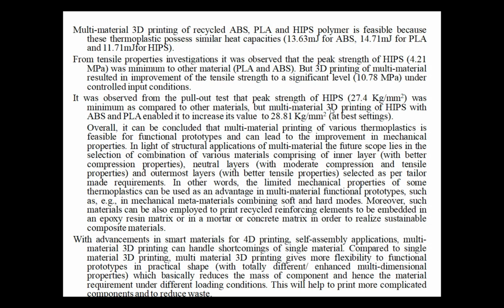If you see the data otherwise, with this type of combination, having multi-material printing of ABS with PLA and HIPS, and then the particular layer which should be kept lower, which should be kept in the middle, and which should be kept on top, I can actually select the composition and the final behavior in the form of the mechanical properties, right? So what I can say, I can also have a self-assembly type application.